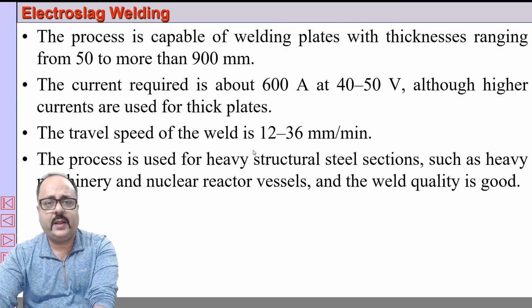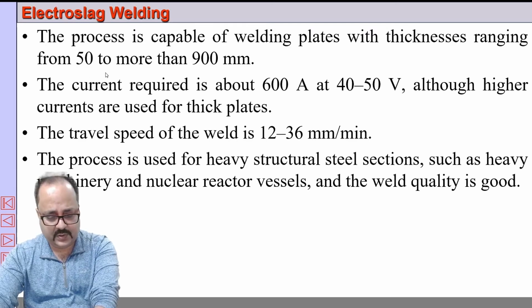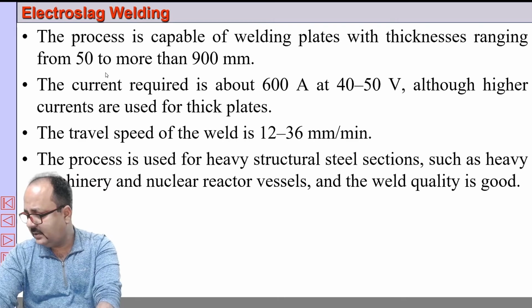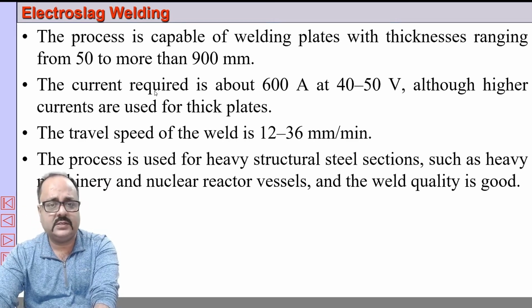So the process parameters: high current, around 600 ampere, very high, voltage 40 to 50 volt. Travel speed is around 12 to 36 mm per minute, and thickness, as I have said, from 50 mm to a large thickness of metal can be welded by this process.